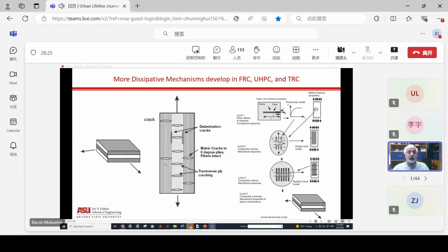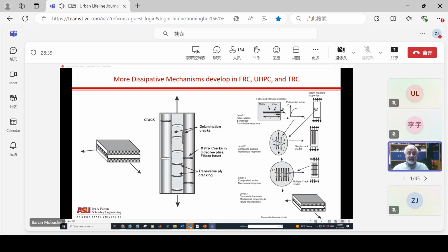So this allows us to play with a system where we make composite laminates with different orientations of continuous fibers. This is the area of textiles that I will talk about. And when you look at the microstructure internally, we see all of these microcracks that have formed. We can also try to develop a sequential system where you have a fiber pull-out mechanism. You take the energy of that, put it back into the system, and calculate how much energy is required to grow this crack. Even when it grows, you ask how many more cracks like this I can put in there. So we get these parallel cracks. These account for doubling or tripling the strength in tension.